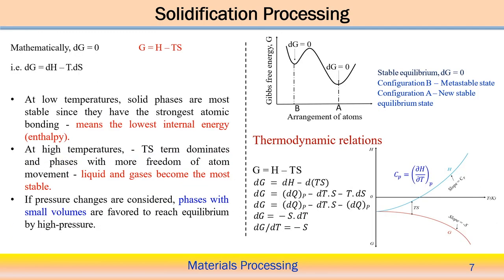Mathematically, we can say that G equals H minus TS. If dG tends to 0 or equals 0, then we can say that it is a more stable system. We see that dG equals dH minus TdS, where we are not varying the temperature here, but holding one constant temperature, and there is a variation of the entropy, dS. So if we try to make dG equal to 0, that is, the change of the Gibbs energy is 0, it means that the system is more stable.